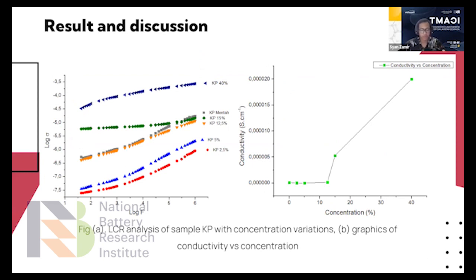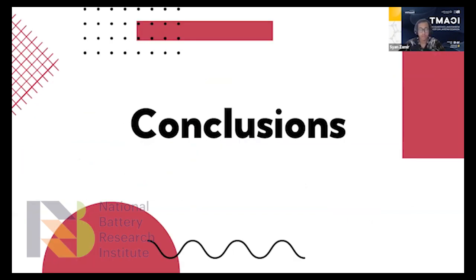In the graph of the result of the LCR test at frequencies from 42 hertz to 1 megahertz, it can be seen that there is a difference in the graph and calculation results, where samples that have gone through the hydrothermal stage have higher conductivity than the raw samples. The higher the concentration of hydrothermal samples, the higher the conductivity it also has, as shown in chart B. So we come to the conclusions.